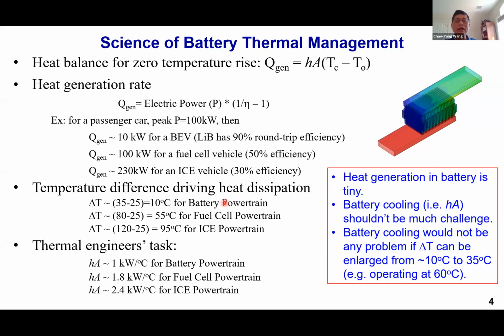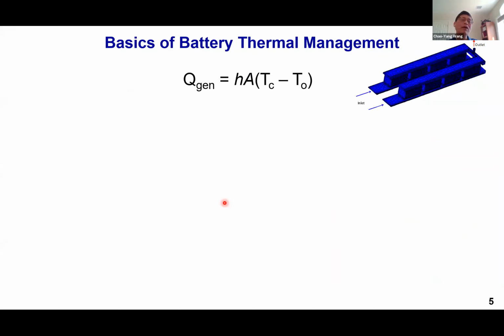numbers, right? And if we can further increase the delta T for batteries from 10 degrees right now to 35 in the future, and assuming the battery would operate stably at 60 degrees Celsius, then the H times A value will be an order of magnitude lower than that for ICE. So we probably can make the battery thermal management problem go away that way, right?